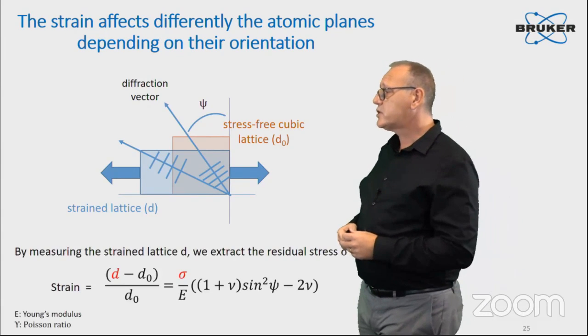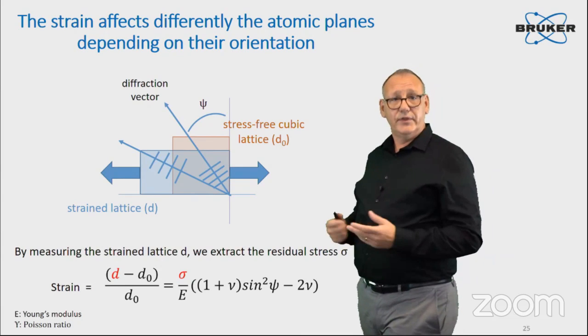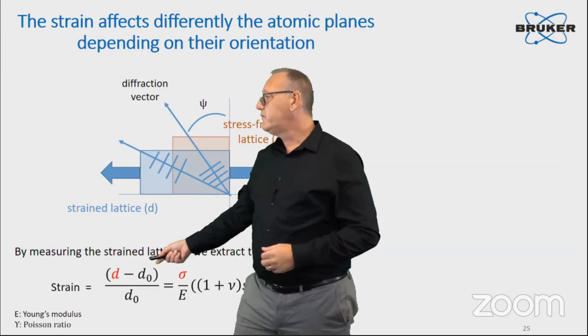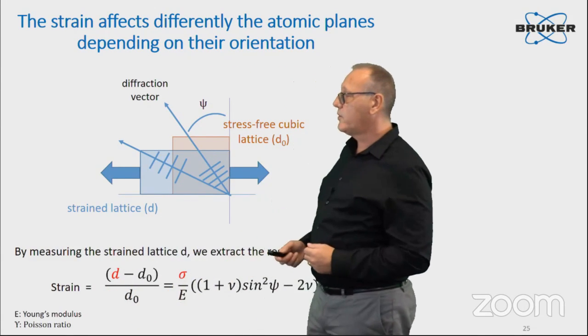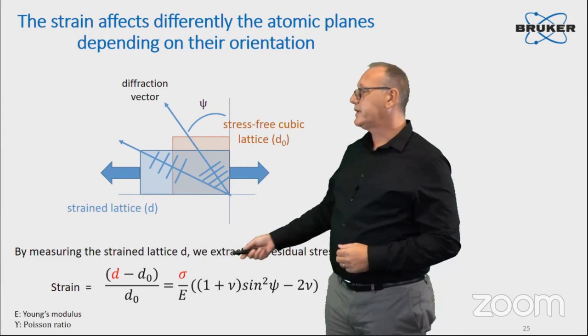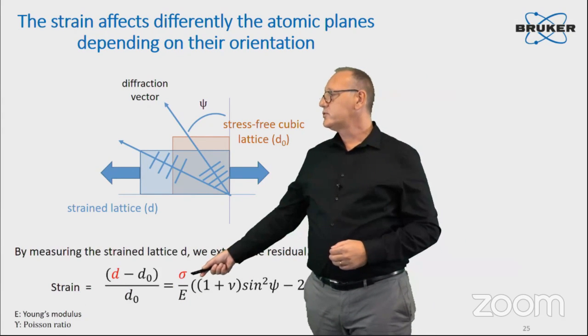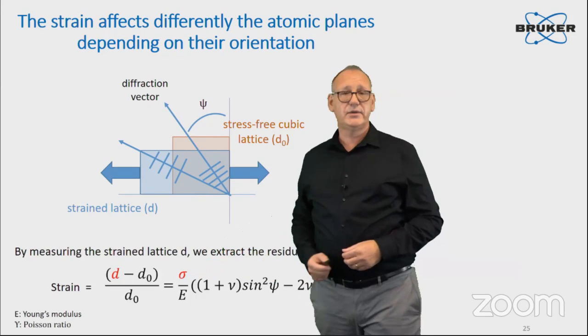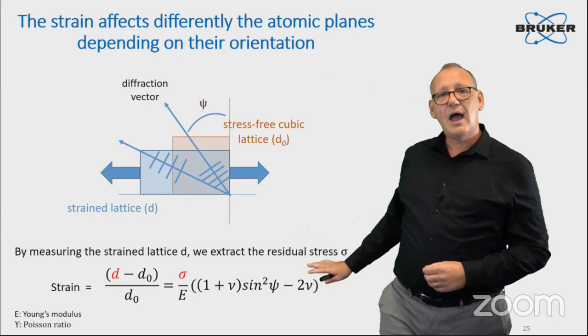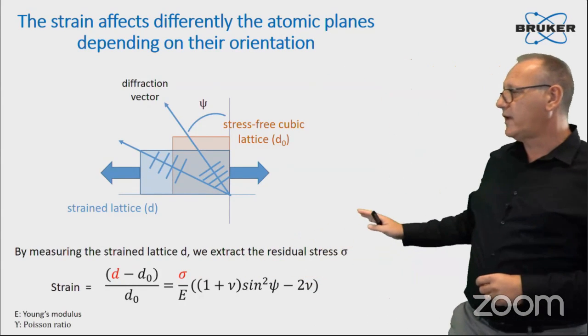So what we are measuring with X-ray diffraction is the d-spacing. And if we involve with the elastic theory some elastic constants of the material, we will be able to extract the residual stress in our material. So we will have to see how we can implement this in our final refinement model.